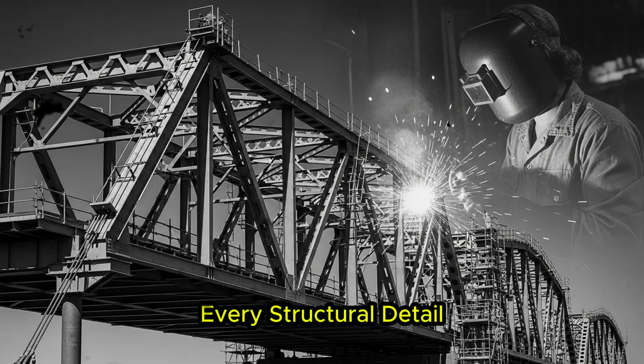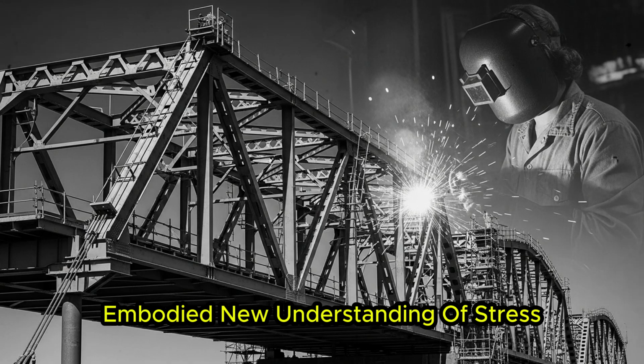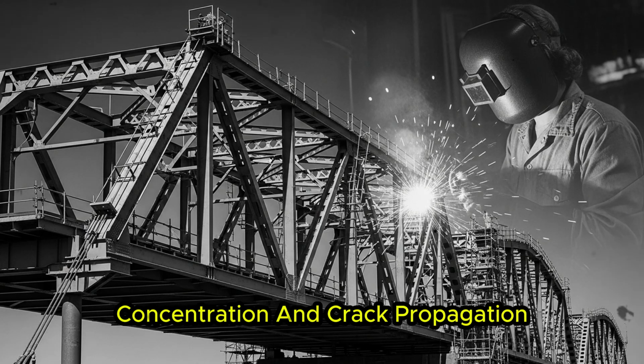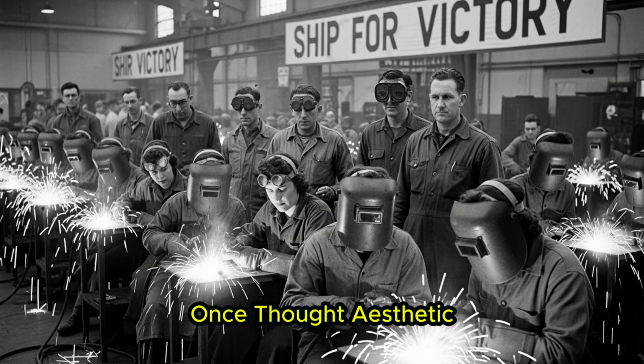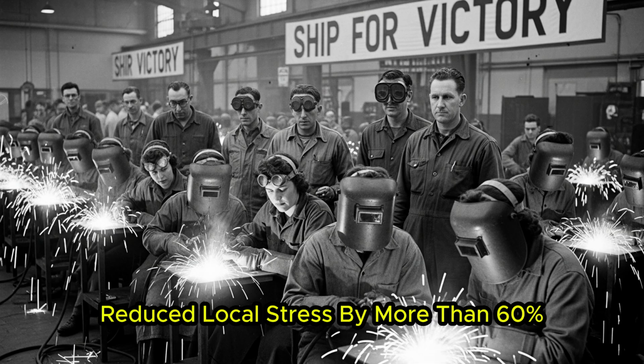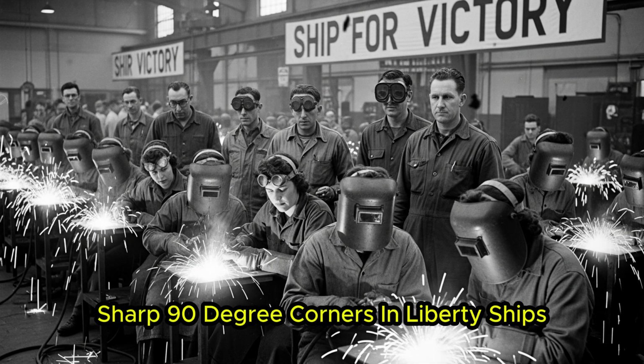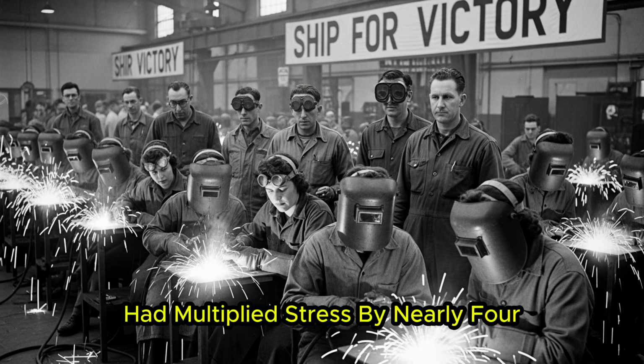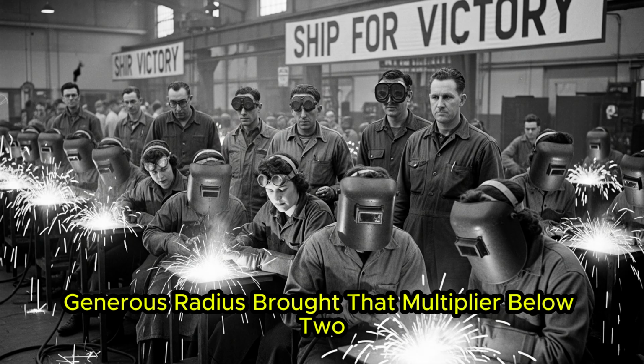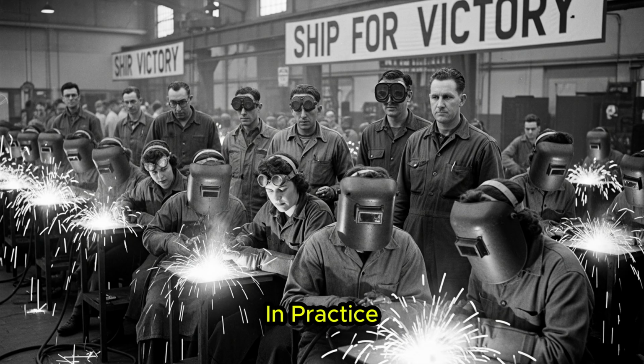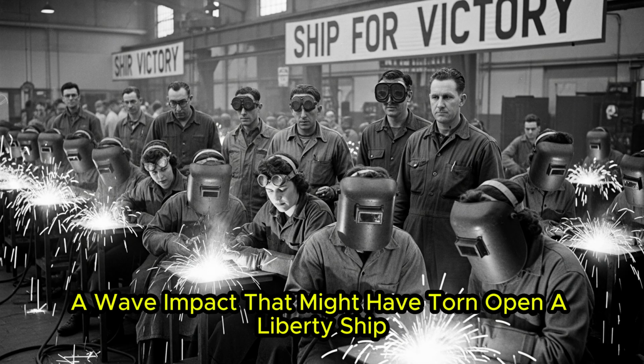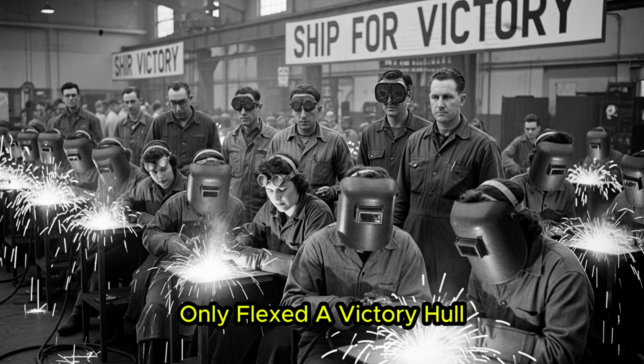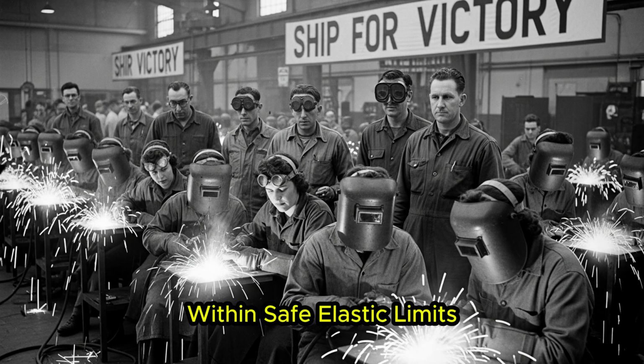Every structural detail embodied new understanding of stress concentration and crack propagation. The rounded hatch corners, once thought aesthetic, reduced local stress by more than 60%. Sharp 90-degree corners in Liberty ships had multiplied stress by nearly 4. Victory ships' generous radii brought that multiplier below 2. In practice, a wave impact that might have torn open a Liberty ship only flexed a Victory hull within safe elastic limits.